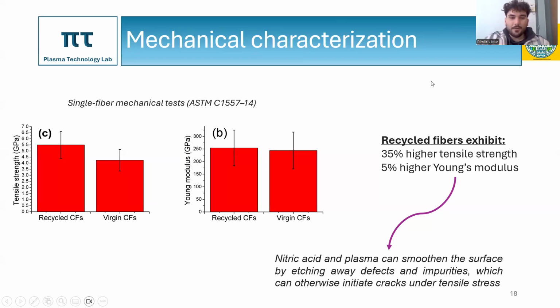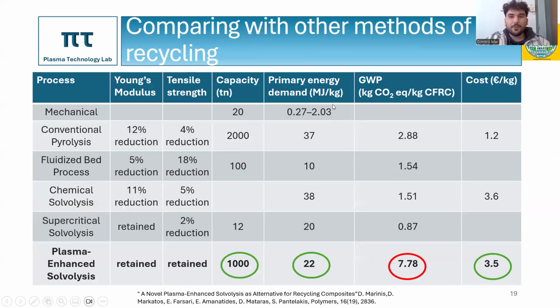But someone will ask, how can the recycled fibers be better than the virgin fibers? And the answer to that is actually heavily mentioned in the literature. And it is because nitric acid and plasma can smoothen the surface by etching away defects and impurities, which can otherwise initiate cracks under tensile stress. Besides the characterizations, we try to compare our method with other recycling methods. And we found out that the energy demand and the cost of our process is comparable to the other methods, but the GWP is still very high, so we need to do some more optimization.